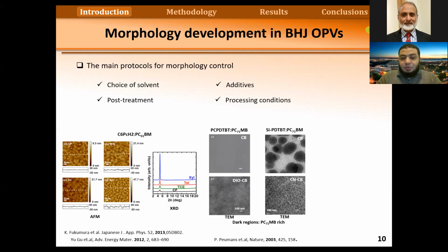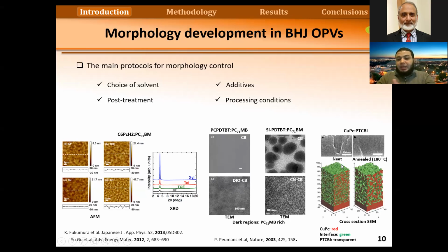So when we use additives, we induce separation. They start to separate into different domains. For another case, when we cast without additives, we have very large domains, but this is bad for solar cells. So we need to use some additives to make the domains smaller. And we can also use some annealing treatment in order to induce these kinds of changes. So we can use different processing strategies to control the microstructure.